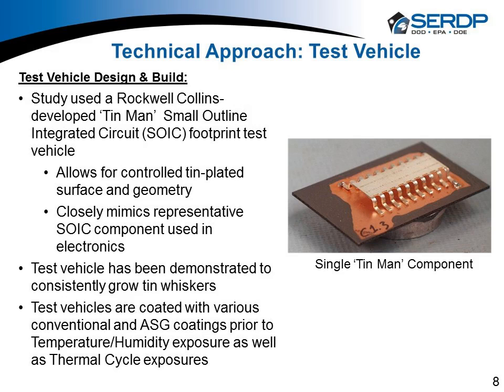If you go to slide 8, our primary test vehicle for all the testing in phase 1 and phase 2 is what we call Tinman. We needed a component I could put in the scanning electron microscope that would not charge up, but I also wanted a component that very much mimicked and was representative of other components I find on my electronics assembly. So we essentially made a 14-pin SOIC, a small outline integrated circuit, and it's all metal. We're able to take this and coat it with bright acid tin plating. It plates very well, and bright acid tin is one of those things we know in the industry that grows whiskers like chia pets. So it made great for having a control, because if your control doesn't whisker, you don't know anything else about the other variables in your test.